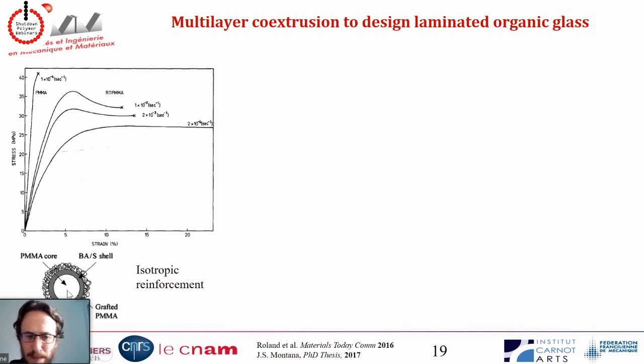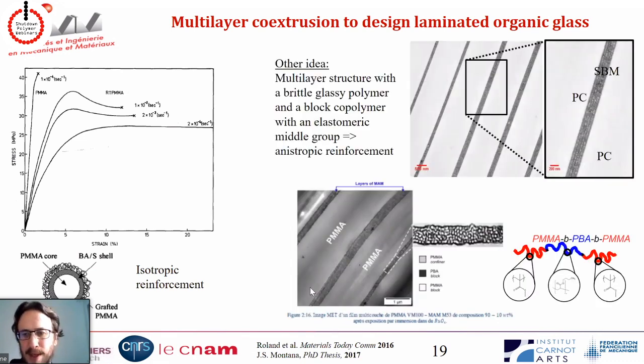But instead of having a rubber particle, we tried to make layers of rubbery materials. To do that, we used not really direct rubber material, but tri-block copolymer to improve the affinity, again, in the same manner as here, to improve the affinity between the rubbery block and our matrix, which is PMMA. And with this multi-layer system, you can see that we have layers of PMMA and in between layers of our tri-block that self-assemble to create these really nice structures.